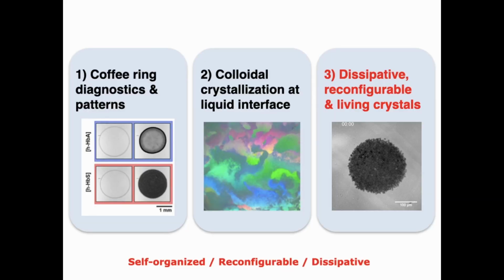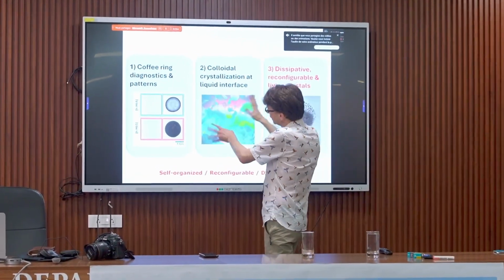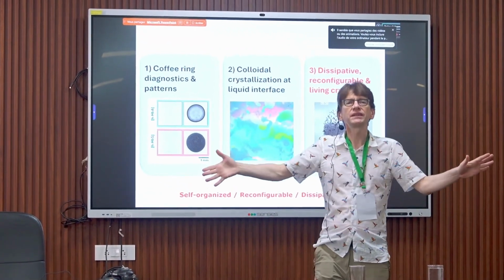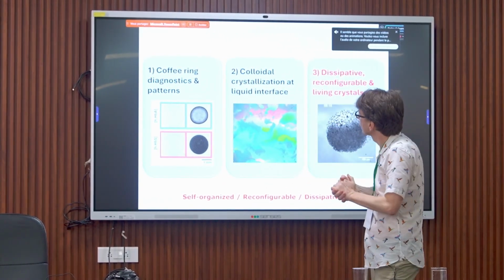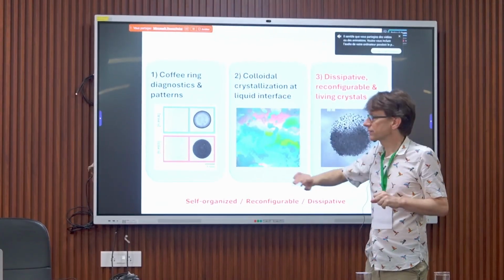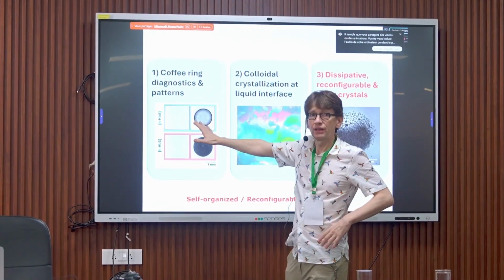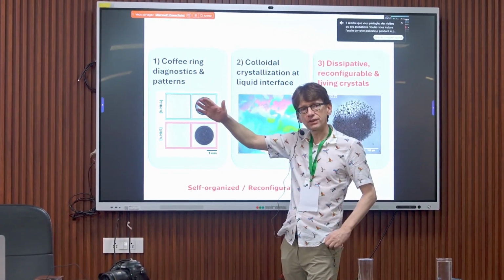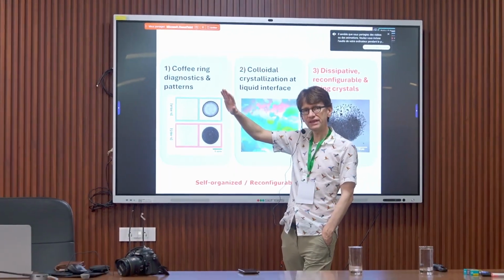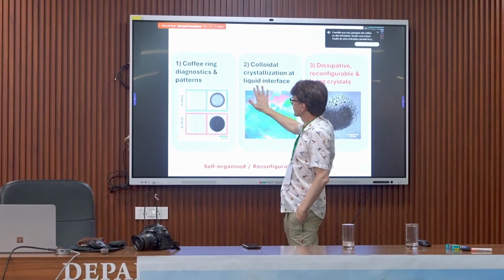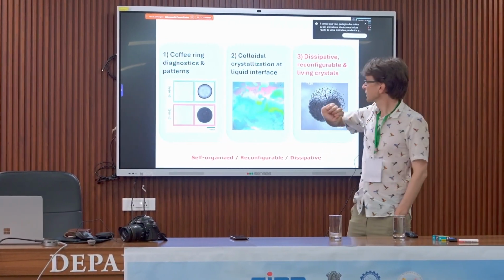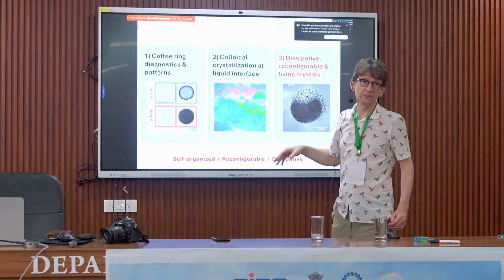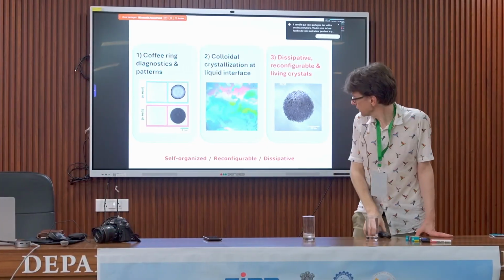Okay, so you see that we started from coffee, where it's very large-scale patterning. We don't have any interaction or any local organization. This was mainly controlled by surfactants at moderately high concentration below CMC, but let's say CMC over 10. And then if you go to CMC over 1,000, over 10,000, you can start to have some very interesting self-assembly behavior where you can crystallize the particles.